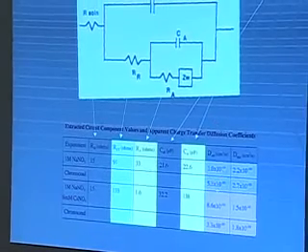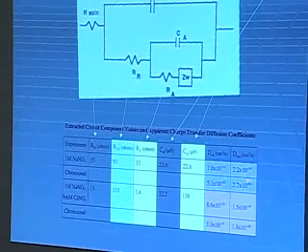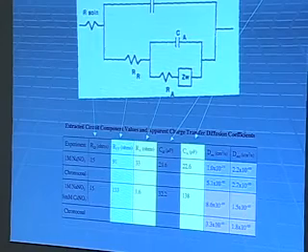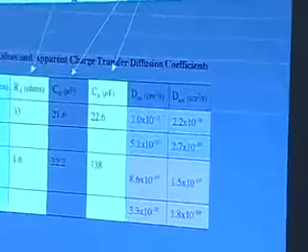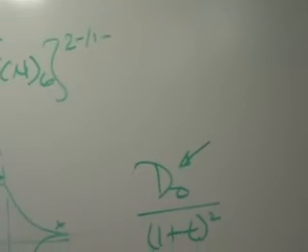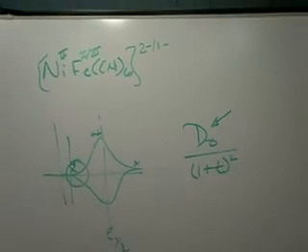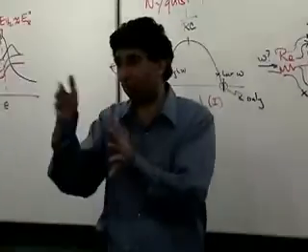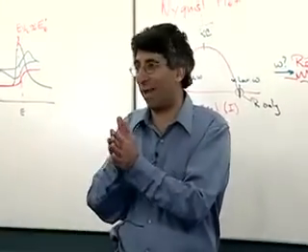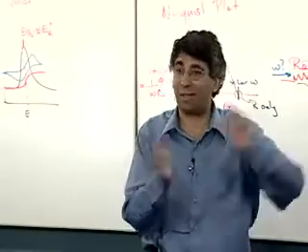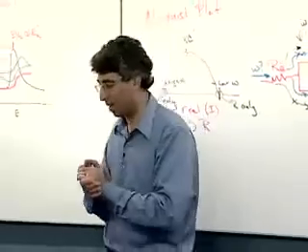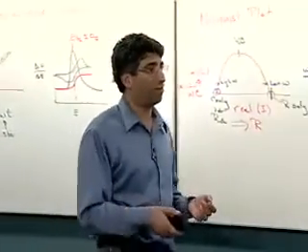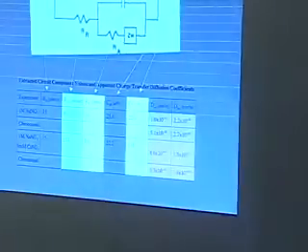And we notice now that when we take this at early time and compare it to these numbers here, the comparison appears pretty good. There is some difference, but remember, we are doing a slight perturbation here, and we are making an approximation here. And so we conclude that this looks all very consistent, and that the model I presented to you last hour, where we have this change in lattice, the lattice expanding or contracting as we do the redox process, and hence the ability of the ions to move through the lattice changing, is consistent. And when we freeze out that lattice motion, if you will, which we're doing in this AC experiment, then we lose the time dependence. We're able to pull out a diffusion coefficient in the normal way, and that diffusion coefficient seems to match up pretty well with what we get for the early time chronocoulogram.